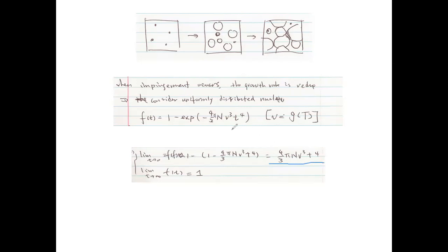On the other hand, if t is very large, when t goes to infinity, the system has to achieve equilibrium. In this case, we consider the whole system to have already completed its transformation, so f has to equal 1. And again, this is consistent, because you have a minus positive large number in the exponent, and this second term goes to 0 as t goes to infinity. So you're going to recover 1. So this is very consistent.